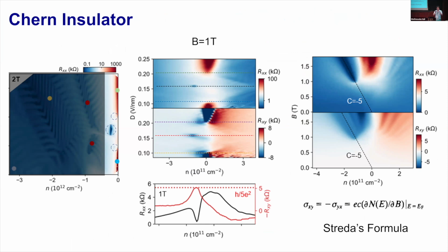And there may be some critical field that you cannot distinguish this one from the other, because you mentioned this one is from this Dirac node, this Fermi inversion. But in the very strong magnetic field, the magnetic energy is comparable to this whole flat band energy. Then things may change. I wonder when you see this change. Yeah, I would say it's probably on the order of like 7 or 8 Tesla. They start to be smeared somewhat equally.